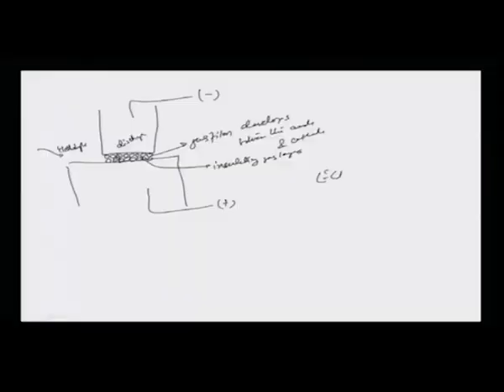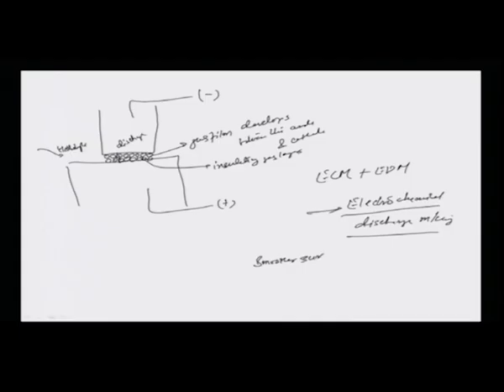And then if ECM is still going on in the same region, there is going to be a self leveling activity done by ECM after the EDM operation is done. So, it is a combination of ECM and EDM, which is actually known as electrochemical discharge machining. And this machining has been able to demonstrate a much smoother surface than normally EDM or ECM standalone, and not only that, this can be done on brittle and hard and insulating substrates also.